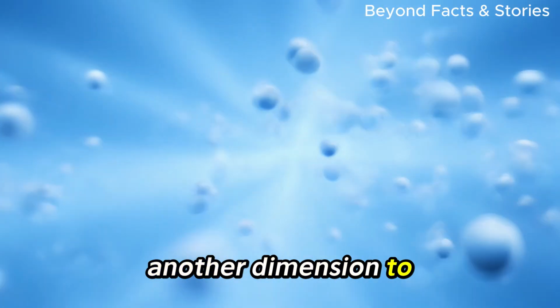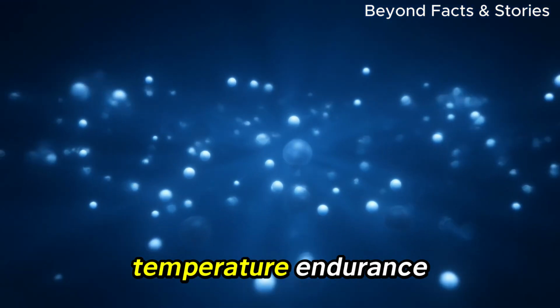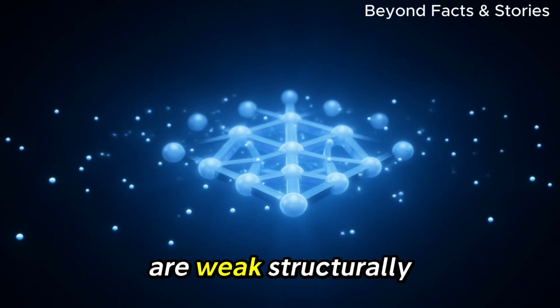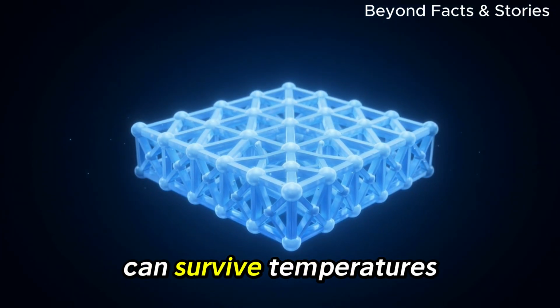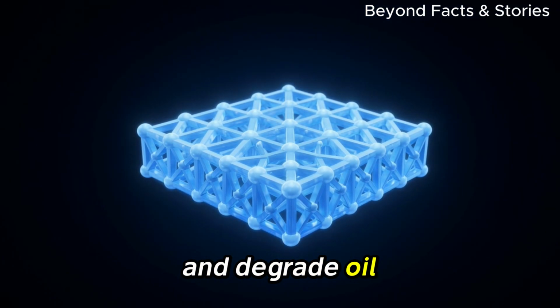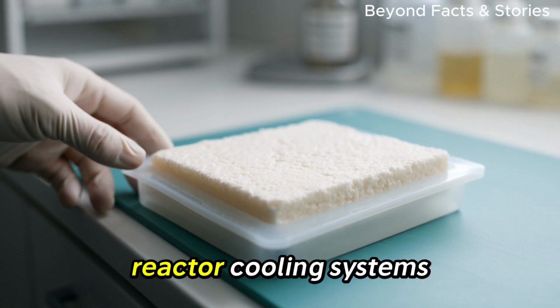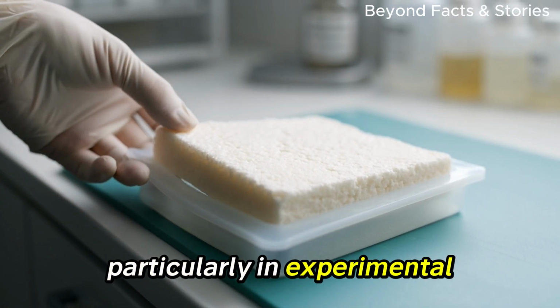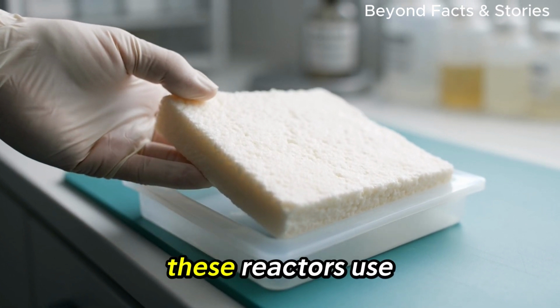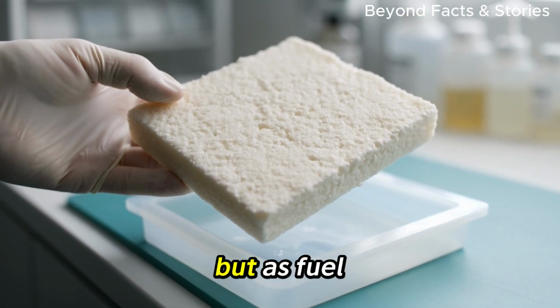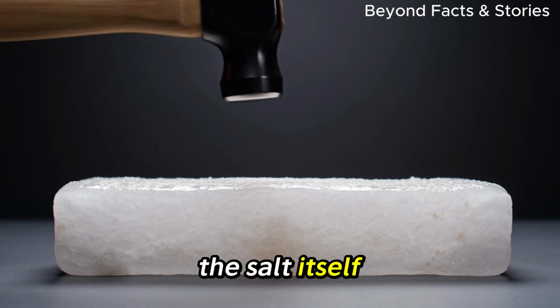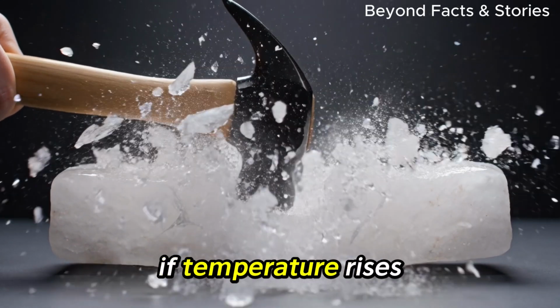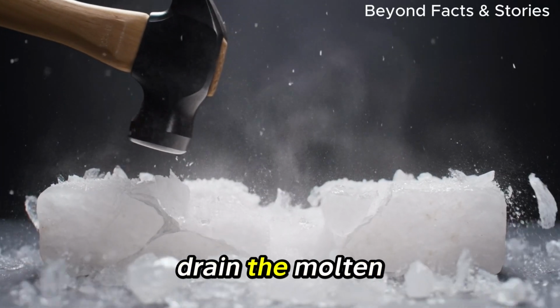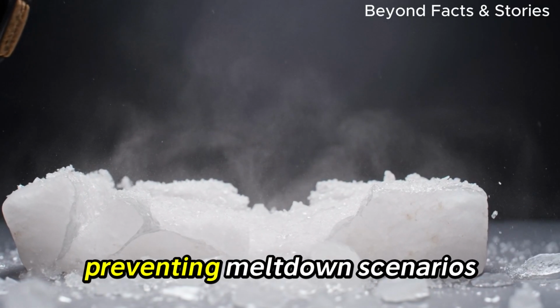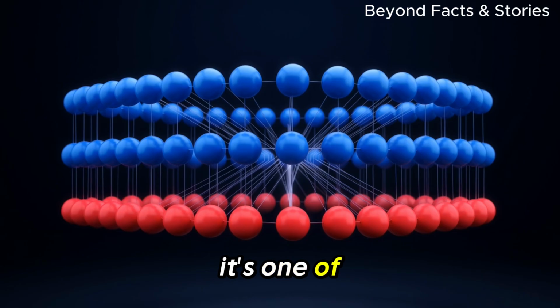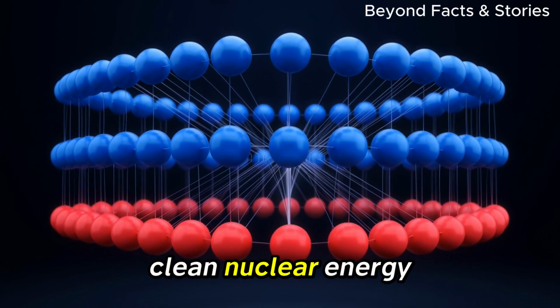But there is another dimension to molten salt that changes everything: temperature endurance. While salt objects are weak structurally, molten salt as a liquid can survive temperatures that destroy water and degrade oil. That makes it ideal for nuclear reactor cooling systems, particularly in experimental molten salt reactors. These reactors use molten salt not just as coolant but as fuel carrier. The salt itself contains dissolved fissile material. If temperature rises too high, the system can drain the molten salt into passively cooled tanks, preventing meltdown scenarios. It's one of the most promising designs for future clean nuclear energy.